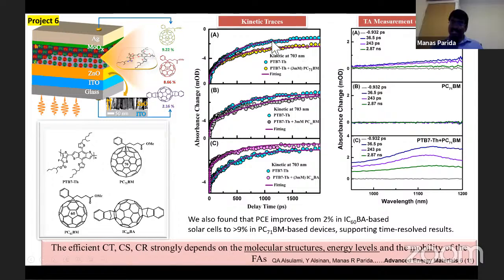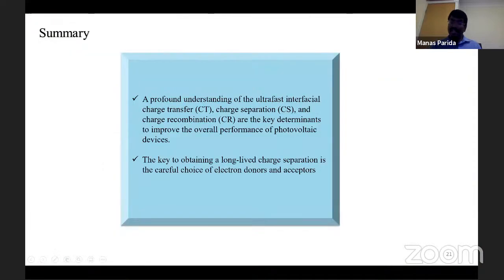And here we can see in kinetic traces that the recovery time for the PC71BM is much longer compared to the other two. That makes sense because it is more efficient, meaning the recombination takes a longer time. That's why you have more efficiency when you make the device. The electron transfer process can also be seen in IR, because once electron transfer happens, you definitely have some cationic or anionic radical formation. You can catch that in the IR region and measure it. So now we understand.